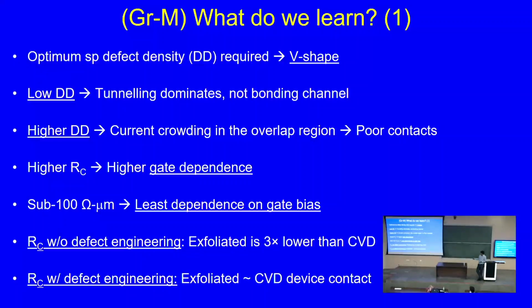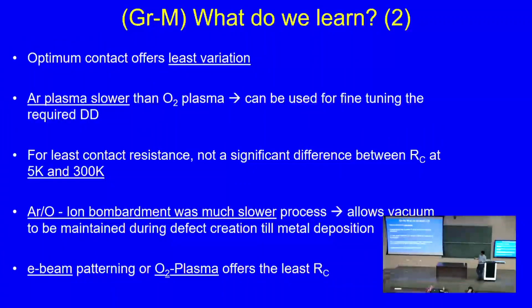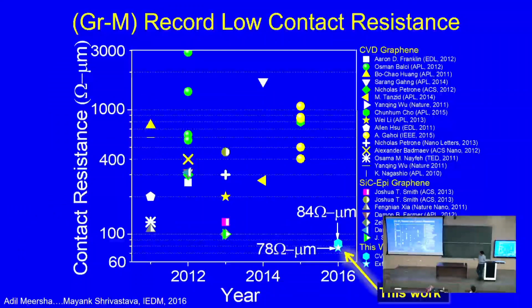In the case where we have no contact engineering, we found that if the quality of the exfoliated material is better, the contact was better. But when we had the defect engineering, there was no implication of the quality of the material. And when we had the optimum contact, we had the least variation across transistors. The data that you saw was measured across 40 samples. Also, when you have the least contact resistance, there was no significant difference between the data at 5 Kelvin versus 300 Kelvin. So this is our data from that time. 78 ohm micrometer was for exfoliated, and 84 ohm micrometer was for CVD.